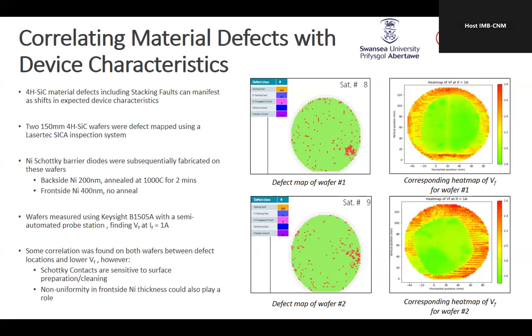And the other type of work that we've done is developing code and software for wafer mapping like this, okay? So you don't typically see this in a university, right? As I say, we're working on wafer level technologies here. And this particular piece of research was trying to correlate device leakage current. So we fabricated a few hundred Schottky barrier diodes across the wafer, okay? And we were trying to match the leakage current to a Candela map of where the defects were in the wafer. And we got some reasonable success, okay?